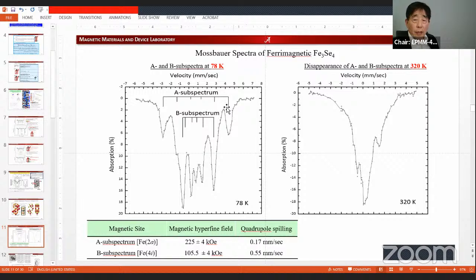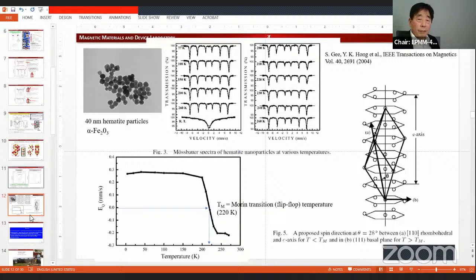And also we can analyze this spectrum and that spectrum to identify the quadrupole splitting. As you see here, the B site has a quadrupole splitting fairly higher than that. That means the B site iron has been more distorted than the iron situated at the A sublattice right here. That's what we can understand from that.